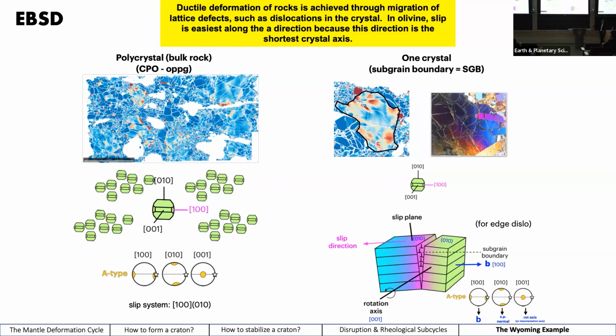So ideally, when we do EBSD on many, many grains in a sample, we plot all of those orientations on one pole figure. We would get something like this if we make some assumption about what we think the shear direction is, which is often very difficult for xenoliths. If we do the same thing for lots of individual olivine grains that have subgrains, we should hopefully get the same answer that we get for the bulk rock, because that means that this rock was deforming under conditions where we would yield the same active slip system.